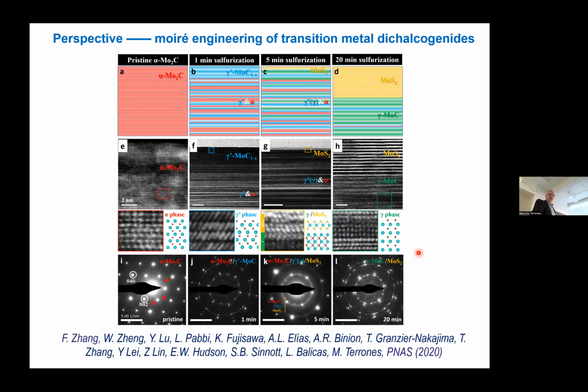So this is just to show you the degree of the molysulfide. We put it in different colors. You can have molysulfide layers now intercalating, but you have molycarbide, gamma prime and gamma molycarbide. And we have here mainly gamma molycarbide, a few gamma prime, and then mostly gamma molycarbide. So this is what we have done.